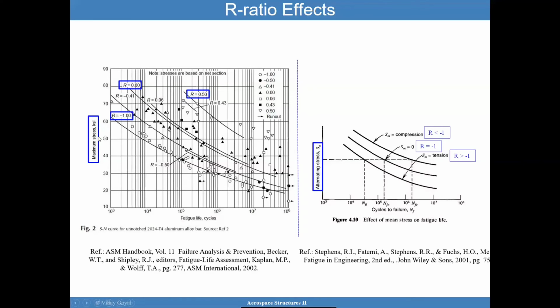And so in general, if I have a maximum stress, say it's 50, this particular curve here is R = -1. So the R = -1 with that particular stress is going to give me a lower fatigue life, okay? But remember that max stress with R = -1 means that the minimum stress is equal to the maximum stress in magnitude. So the range is actually twice this 50. So that's 100. And so that's why you have to be careful here on how you use this particular graph, because this is in terms of maximum stress.